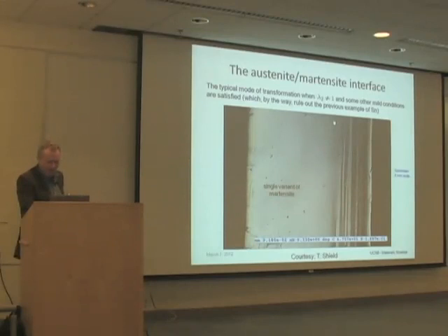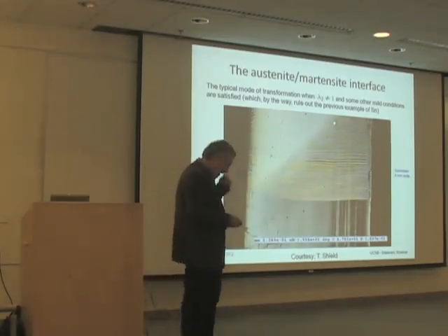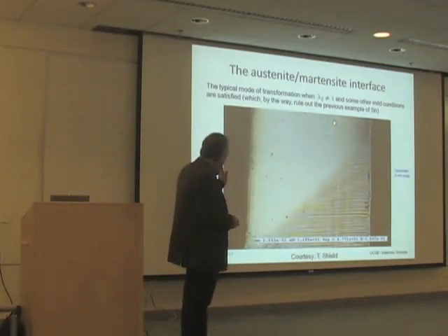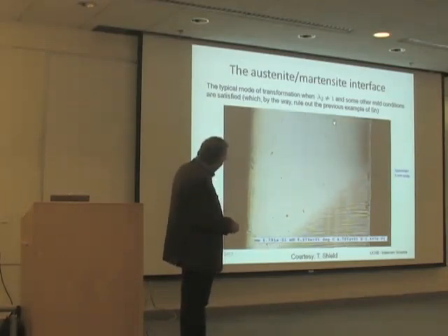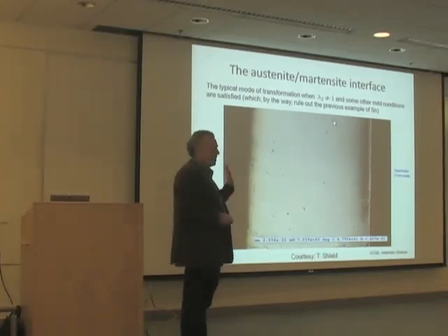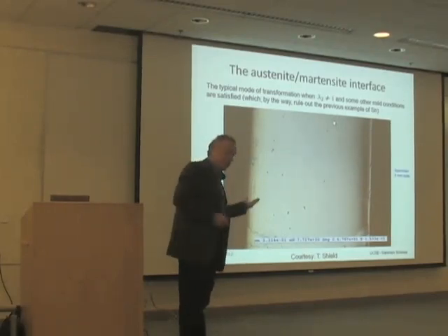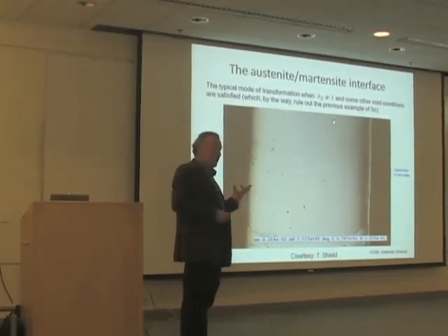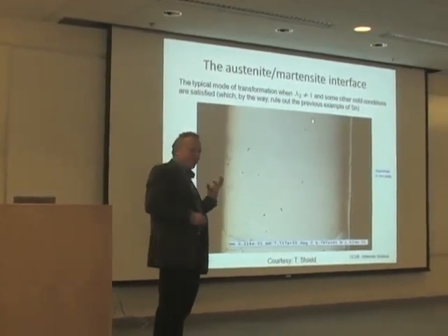And this is what happens when you transform. So that's just heating it up. And the interesting thing about this picture, that's austenite now. The interesting thing about this picture is this is a microstructure of martensite that appeared. So by transforming from austenite to martensite, the new phase is martensite. But in order to get there, it created a microstructure in the martensite. The disappearing phase was forced to create a microstructure.